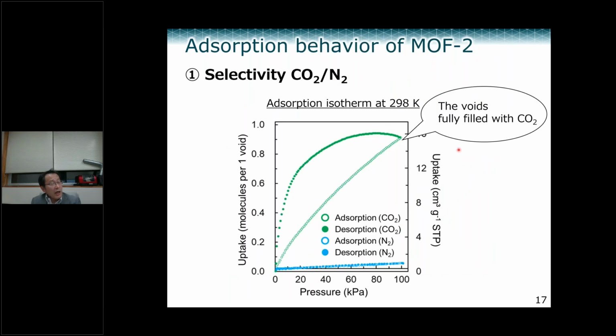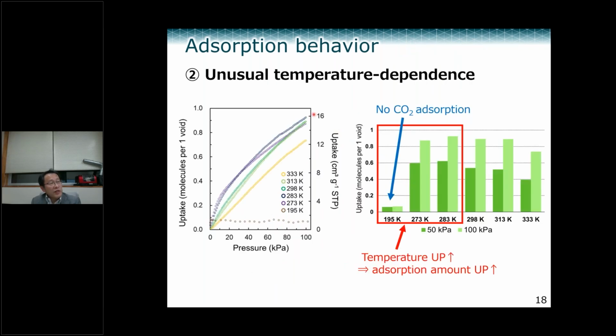This isotherm was measured at room temperature, okay? So this is also another important point. And the selectivity is quite nice over CO₂ and dinitrogen. So we wondered, what is the mechanism of this material? First, we checked the temperature dependence of the sorption amount.